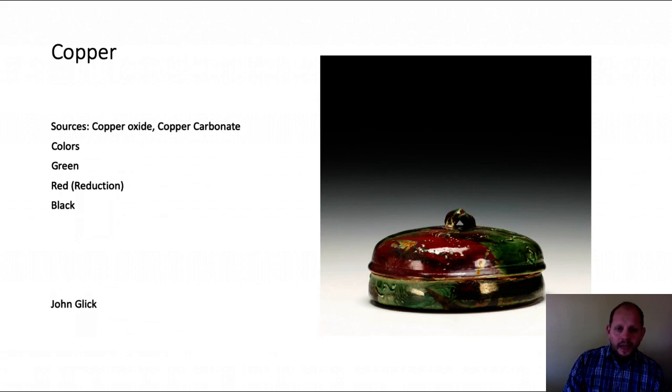And in raku firing, you can have an abundance of copper in those glazes, and you'll get a really wide color response, including anywhere from copper penny hues to greens, magentas, reds, yellows. And then in normal high fire reduction glazes, you can have hues anywhere between green, blue, and red. So, okay, moving on.